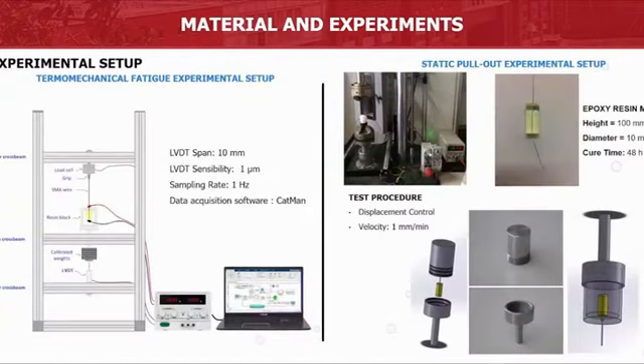There are two different experimental setups that we have made to evaluate the performance of the adhesion on the surface. One is for thermomechanical fatigue purpose, and is composed of an aluminum frame, and the sample is passed between a load cell and a linear variable displacement transducer. There are also a set of calibrated weights that we use to perform different fatigue tests with different constant load conditions. The system is also composed of a programmable power supply and a data acquisition software.